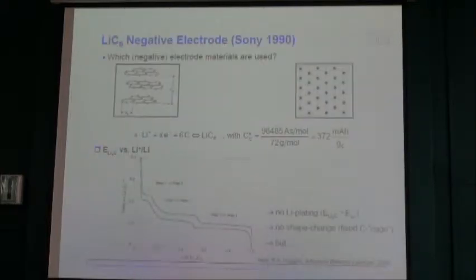Okay, so this is how graphite actually works. If you look at graphite with lithium, the graphene sheet is a hexagonal structure, right? Typically a lithium ion goes into every other hexagon. That's why we have LiC6. For 6 carbon atoms, you get only 1 lithium ion. So that will limit your capacity. That's why we have only 372. If you want higher capacity, you should be able to put more lithium onto this network. That's what we did recently. By making graphene spheres, we could put more lithium onto this carbon network. I'll show you that. So this is what we have right now with the standard lithium-ion batteries.